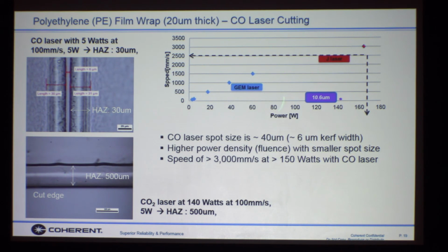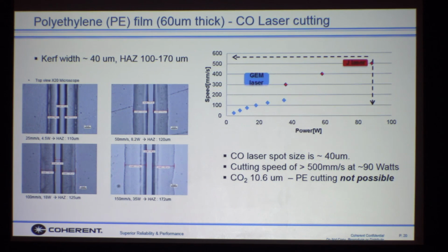drives the process. And so you can see from this chart that we're able to process very thin, this is 20 micron thick, polyethylene at 3 meters per second. You're able to do the same thing with the CO2 laser if you really blast it with 140 watts, okay, but then you get a huge amount of HAZ and curl over. And then once you go to thicker polyethylene, for example, it's impossible to cut with the CO2 laser. It just destroys the material because you're trying to put so much power into the material, whereas with the CO laser, you focus it down tightly and drive the absorption in the material.